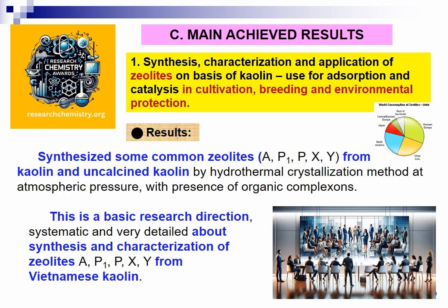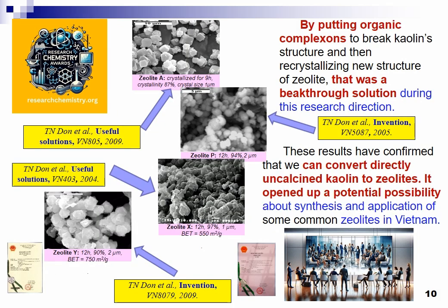The result: we synthesized some common zeolites from uncalcined kaolins by the hydrothermal crystallization method at atmospheric pressure in the presence of organic complexons. This is a basic research direction, systematic and very detailed about the synthesis and characterizations of zeolites from Vietnamese kaolins.